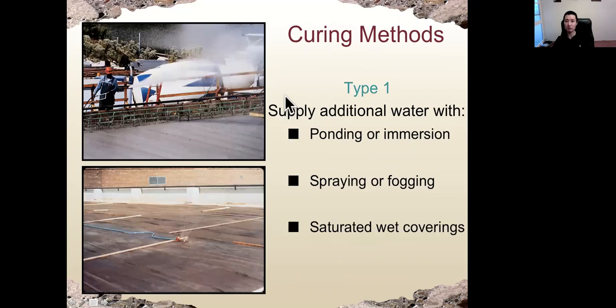Let's look at how we cure the concrete. Probably everybody has seen that before. When we cure the concrete, we need to cover the concrete surface, or we apply some additional water - so that's three types of curing method. The first one, also the best one, is to supply additional water by spray, ponding, or immersion, after the concrete sets. This is the best way to cure the concrete, providing additional water to concrete.